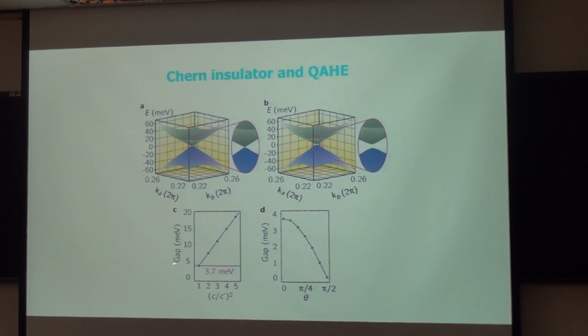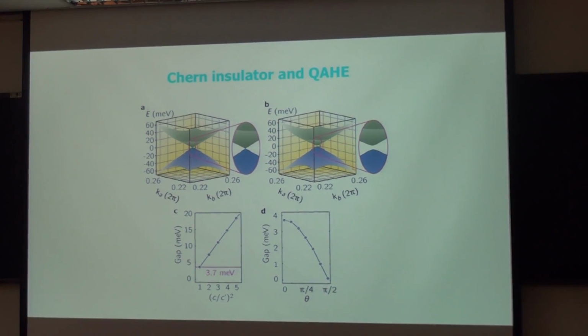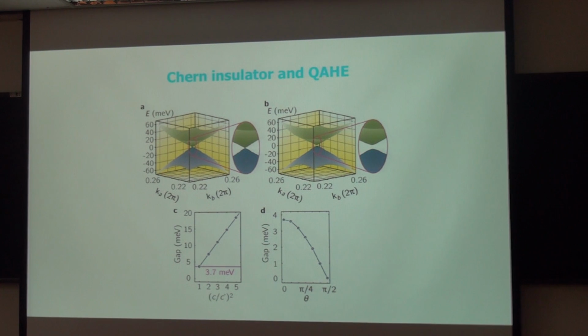And we can find the band gap of the system is 3.7 milli-eV. This is much larger than the experimentally observed chromium-doped topological insulator, and in that case the band gap or the transition temperature is extremely low. So this example provides a very interesting case to realize topologically non-trivial physics in transition metal oxides.